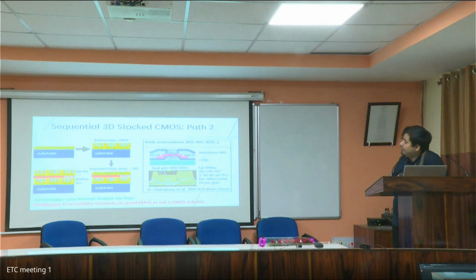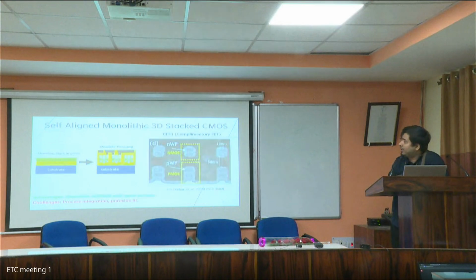This is an example from one of my papers published in the 2020 VLSI conference, where we were depositing tungsten-doped indium oxide as the channel material. We could deposit it at a very low temperature, I mean at room temperature. So the bottom transistor layer was intact, it didn't degrade, and then we were able to fabricate the transistor on the top layer based on that deposited layer. So that's the second path, but both these paths are sequential, right? Because you are making the two layers separately.